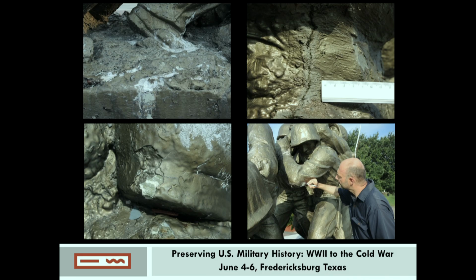Shortly after the sculpture was exposed to the environment of Parris Island, it began to develop cracks and fissures, allowing water to penetrate the concrete and saturate the clay core. I will explain the construction technique shortly on a future slide, but basically it is a concrete shell filled with a type of clay reinforced with steel rebar. Previous repair campaigns have been carried out on the sculpture in attempts to address the water ingress into the monument and prevent cracking and breakdown of the coatings.